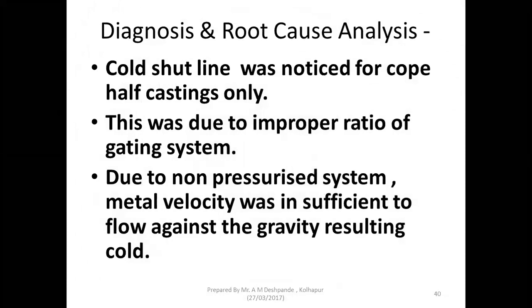A cold shut line was noticed for the cope only, because all the patterns were numbered 1, 2, 3, 4 up to 24. During the study, it was noticed that castings in the drag box were all okay. The castings in the cope box only had the cold shut line. This was due to an improper ratio of the gating system. Due to the non-pressurized gating system, metal velocity was insufficient to flow against gravity, resulting in the cold shut rejection.